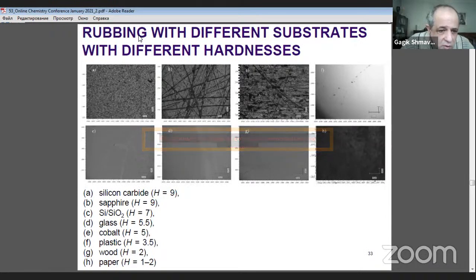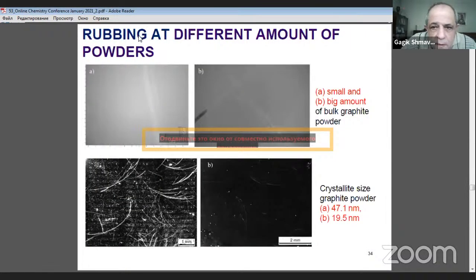Here are a few examples of substrates with different hardnesses. We use different substrates like silicon carbide, sapphire, silicon, glass, cobalt, plastic, wood, and paper. We also use different powders, a small amount of powder and a big amount of powder. In any case, you can see different nanostripes, and there is a transition from multi-layer nanostripes to mono or few-layer nanostripes.